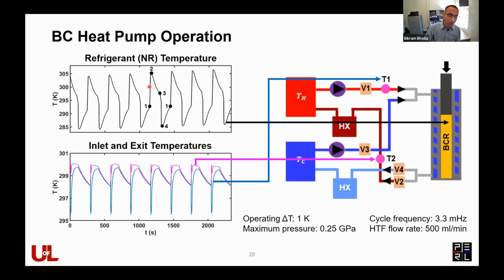So for the barocaloric core, as you saw, this is for a pressure of around 250 megapascal. You can see that the barocaloric media goes from around 285 to 305 Kelvin, around 20 Kelvin. So that sets the upper limit of the temperature span. And so we can change the delta T by controlling the thermal reservoirs to mimic whatever application we want to look at.